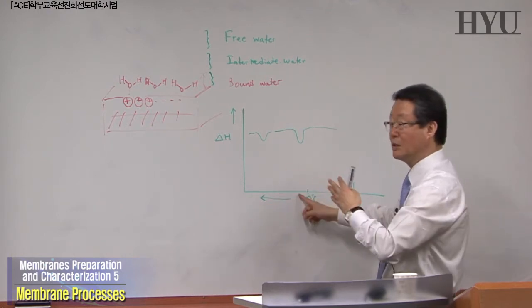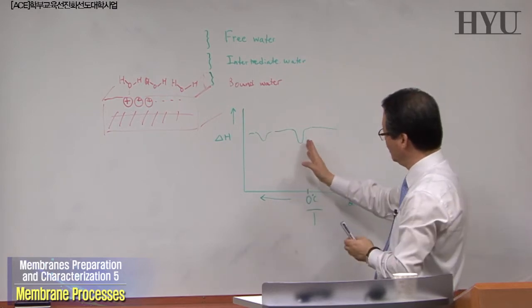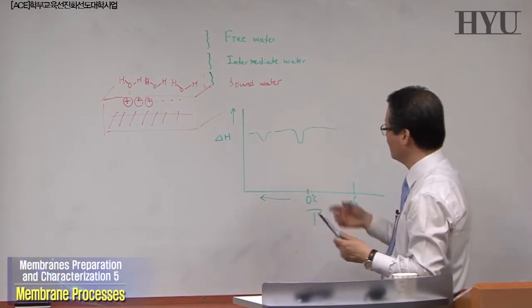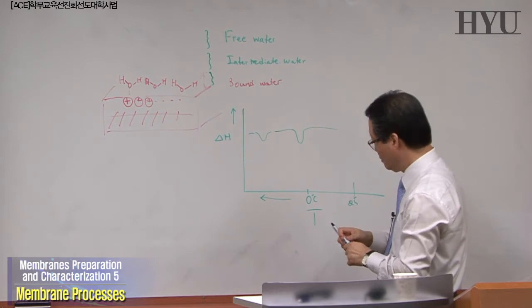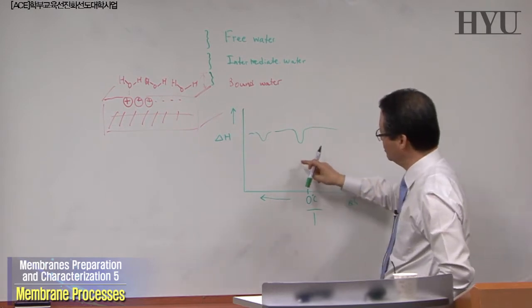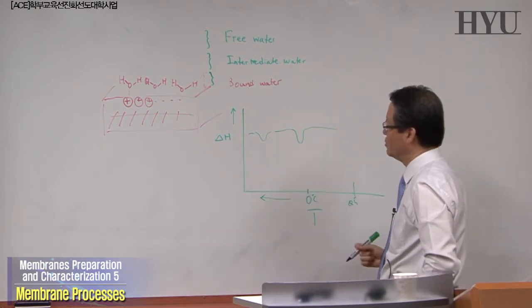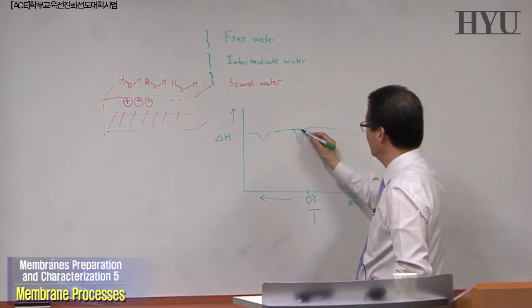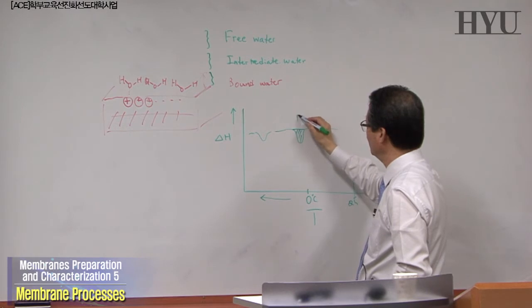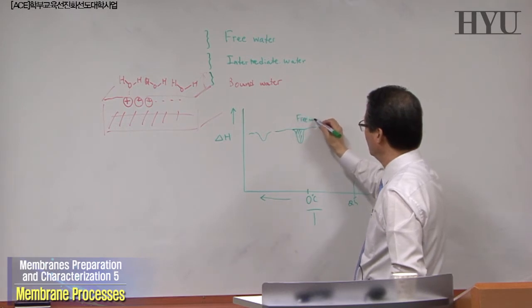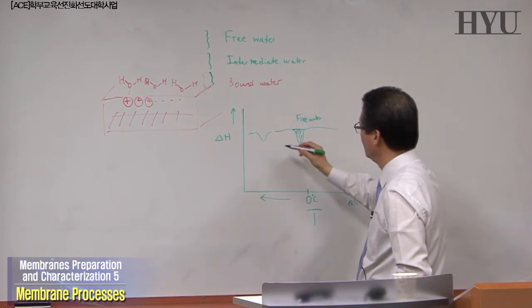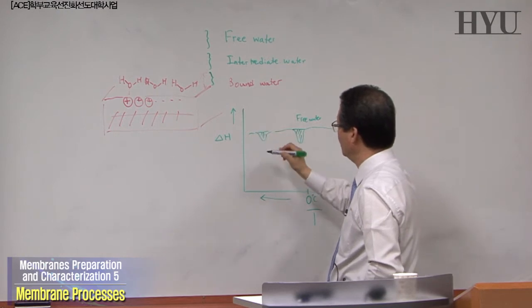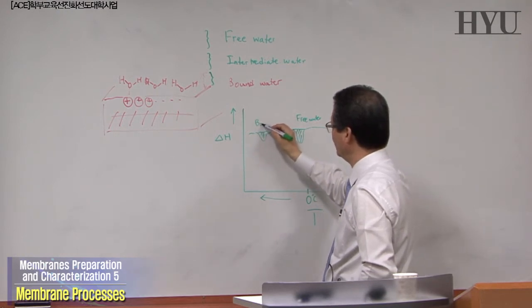So the rate will be changing, of course. Anyway, if you slowly cool down and observe these two peaks, then the first peak is due to the free water. The second peak is usually due to the bound water.